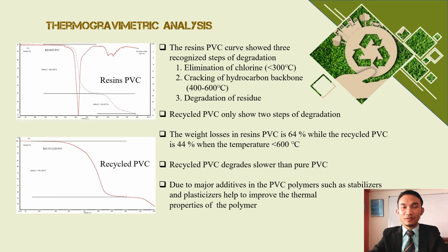From the result, the recycled PVC curve only shows two steps of degradation. The weight loss in the resin PVC is 64%, while the recycled PVC is 44% when the temperature is below 600 Celsius. In this case, recycled PVC degrades slower than pure PVC due to major additives in the recycled PVC polymer such as stabilizer and plasticizer that help to improve the thermal properties of the polymer.